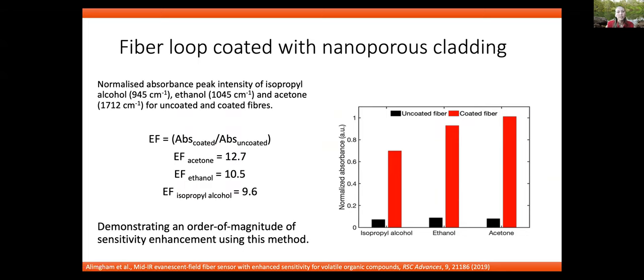And this is because different VOCs, first of all, have different size. They also will undergo capillary condensation in the nanopores in different concentrations and different temperatures and different environments. So it is also very important to understand how the specific chemical will interact with the surface. So chemicals that are more polar, like ethanol or acetone, are the ones we measure. They have a polar oxygen group that will create strong van der Waals interactions with the nanoporous silica.